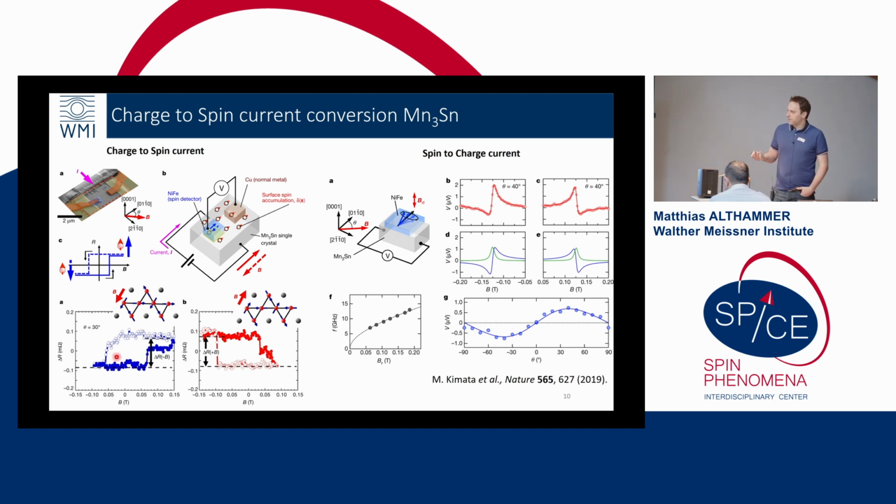So there's indeed an effect that you see here in the structure due to the charge current leading to a transversal spin current in the system. They also did the opposite way around. So here you have charge current drive. Here now they switch to the spin pumping geometry where we already heard some comments about previously. So the permalloy here is driven by a microwave field, and now you measure the voltage or the rectified voltage in the end that you get out of the system.